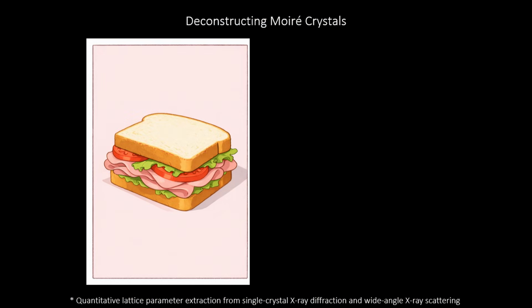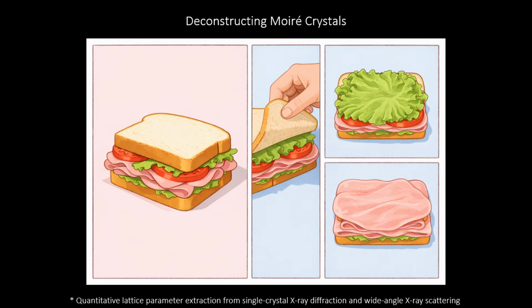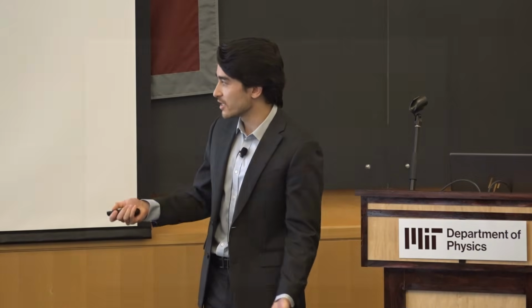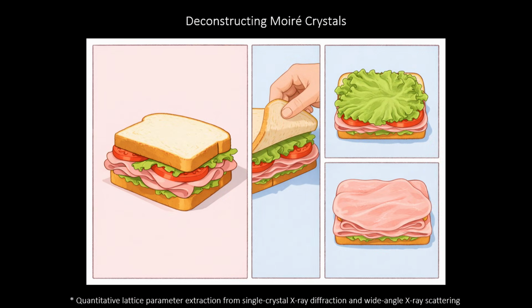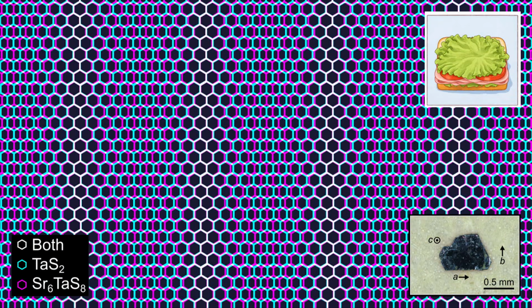But another interesting perspective is to take a top-down approach and to look at peeling back the layers of these Moiré crystal sandwiches to understand what that in-plane Moiré superlattice looks like. So this would be akin to essentially the X-ray diffraction probes we used in order to extract lattice constants, to extract relative lattice parameters, and to simulate the lattice structure in plane. So here's a simulation of X-ray diffraction. This is a good example of one of these Moiré crystals that we discovered. And we're simulating the tantalum disulfide in blue, the Sr6TaS8 in pink, and then when they overlap with one another, it produces white light.